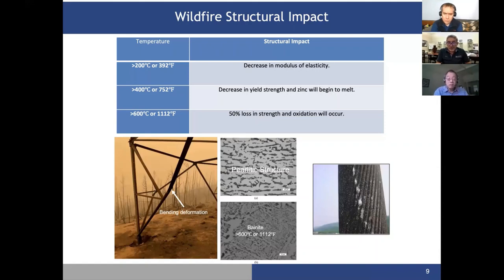The pictures in the middle give you two different microstructures of steel. The one that is normal prior to wildfire, which is called pearlitic structure, A. And B shows a structure that is exposed to wildfire at higher temperatures exceeding 600 degrees. You clearly see there is a difference between these two.